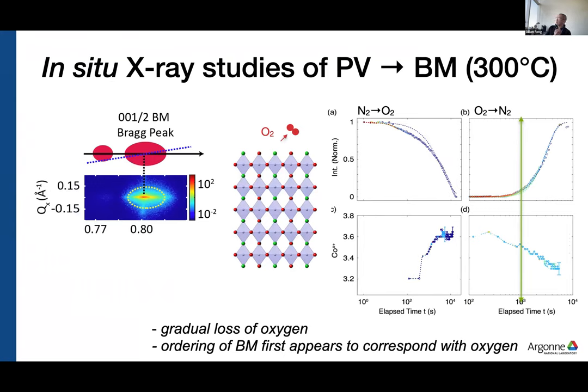And then we switch back to nitrogen. This is again at 300. And you see again that it takes quite a long time. The intensity of the XANES slowly goes up, and the cobalt oxidation state slowly goes down to get back down to around 3.2 plus. It takes even longer than 10,000 seconds.